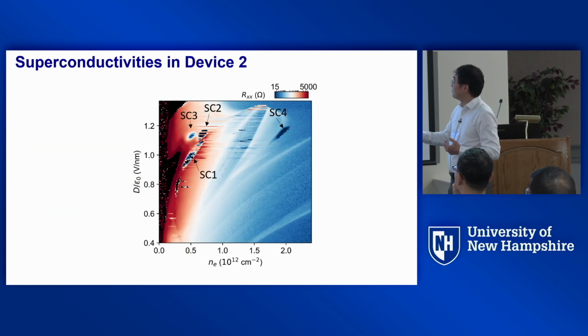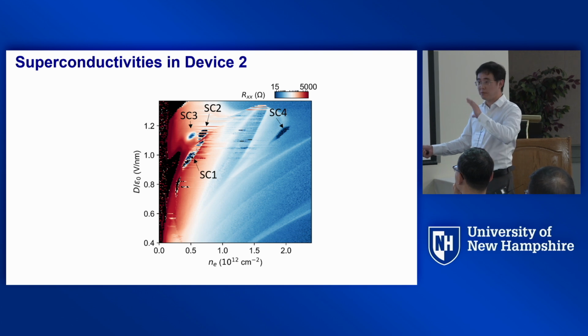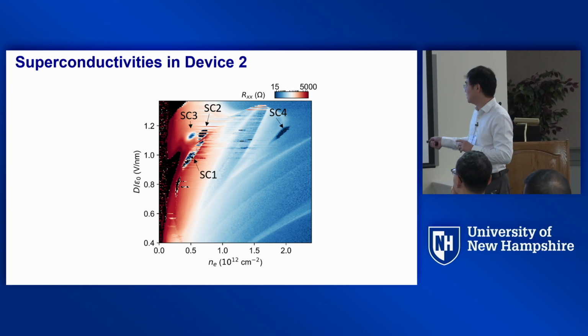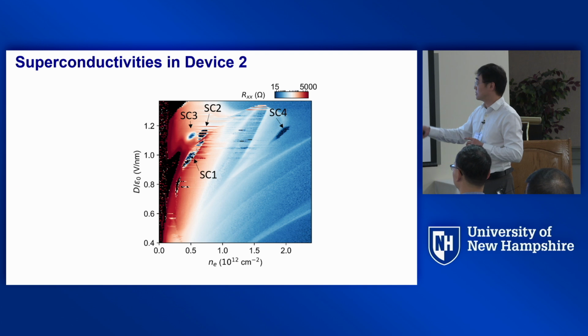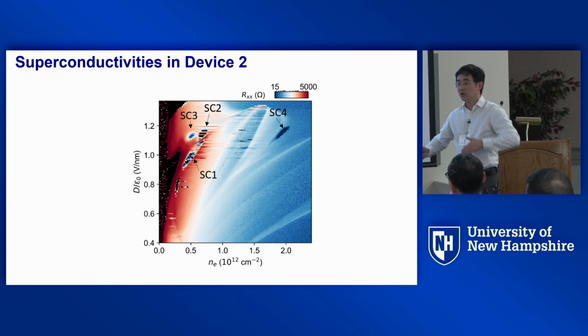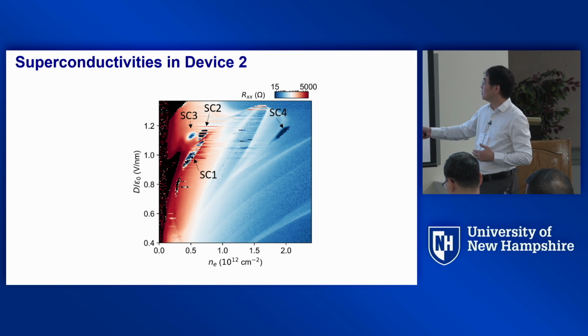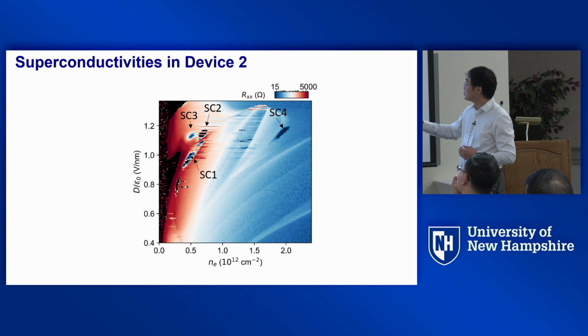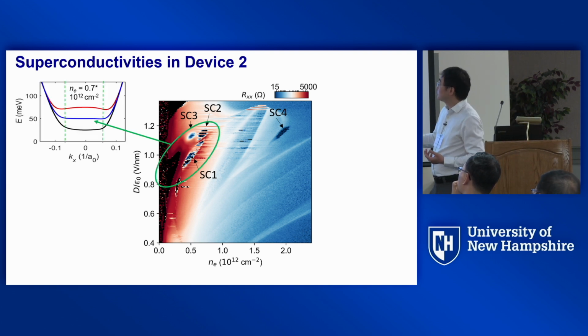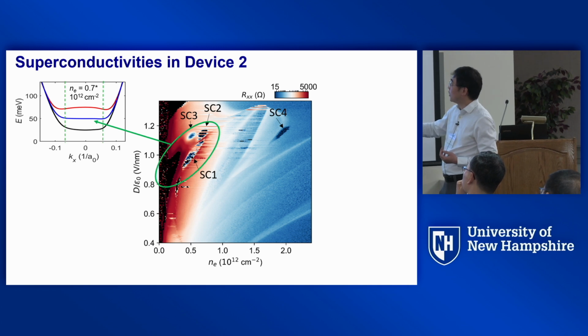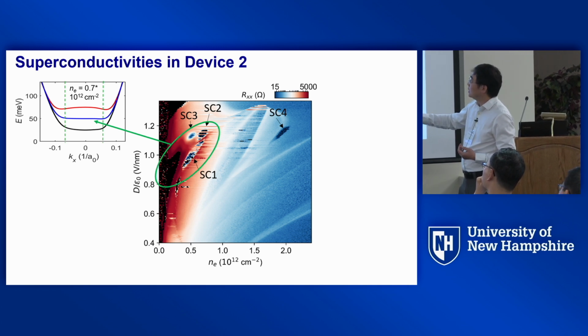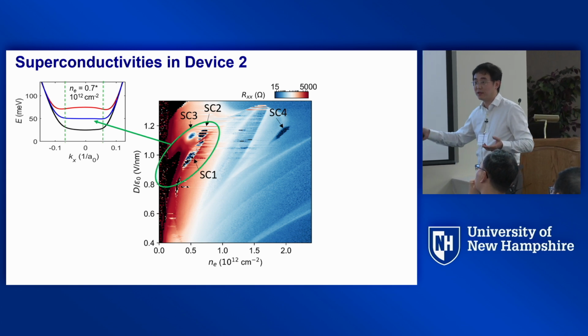So this is from device 2, and you know the trick of tuning top and bottom gate voltage to control charge density on the horizontal axis and the displacement field to open up the band gap. When you open up a gap with 1 volt per nanometer level of electric field, you get 4 regions that seem to go to 0 resistance: 1, 2, 3, 4. And later we confirmed they are all superconducting. This region corresponds to when you have a really flat band, the bottom of the conduction band, and you dope electrons within that flat part of the band.